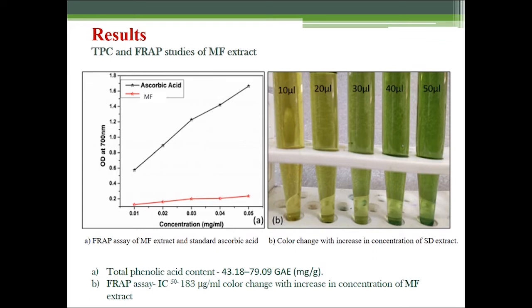Once the extract was prepared, it was subjected to quantitative analysis of the phenolic compounds present in the plant extract. As we know that polyphenols are important constituents of plant derivatives, the aqueous extract of Mussaenda frondosa was found to possess total phenolic content in the range of 43 to 79 milligram per gram of the plant extract.